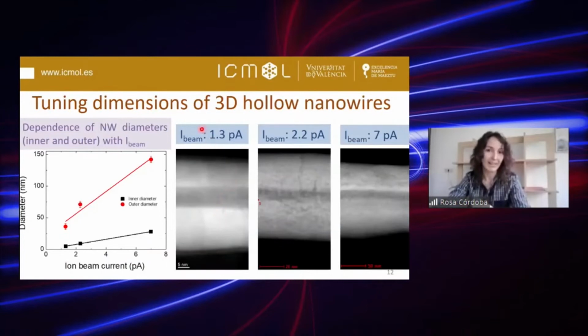So if we modify the ion beam current during the growth from 1 picoampere to 7 picoamperes, we can tune the dimensions of these 3D hollow nanowires. As you can see here in this plot, this is the diameter as a function of the ion beam current. We can obtain very small inner diameters from 5 nanometers to 25, and for the outer diameters, from 32 nanometers to 140. So just by modifying the ion beam current in the growth, we can tune the dimensions of these hollow nanowires.